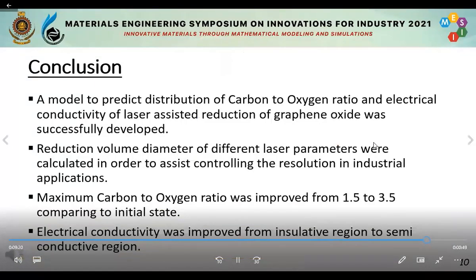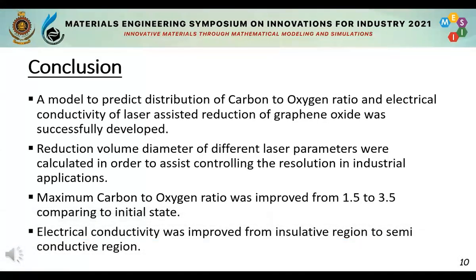In summary, we developed a model to predict the distribution of carbon to oxygen ratio and electrical conductivity of laser-assisted reduction of graphene oxide. Reduction volume diameter for different laser parameters were calculated in order to assist controlling the resolution in industrial applications. Maximum carbon to oxygen ratio was improved from 1.5 to 3.5 compared to the initial state. Electrical conductivity is improved from the insulative region to the semiconductive region.